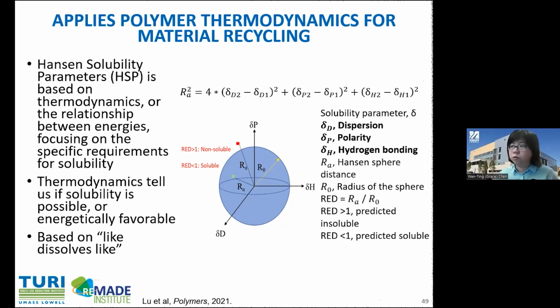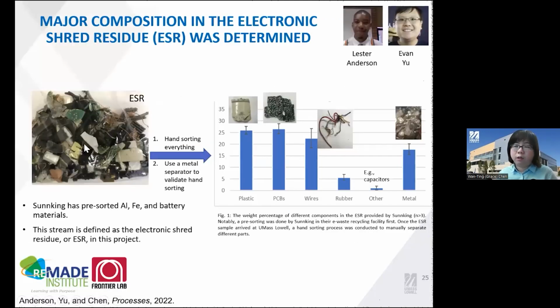So with that in mind, I would like to explain why we need to learn this polymer mixing thermodynamics. With this, for example, if the waste we would like to recover, we know its solubility. Okay, we'll be able to formulate and identify a solvent that could help us extract this specific polymer. And this is especially important for relatively mixed plastic waste, such as the electronic waste that I show here. So this is an electronic waste residue where an e-waste recycling company has already taken those valuable parts. So first we study what's inside of these electronics, and then we found plastic accounts for about a quarter, like 25%. And among these plastics, the majority of them is actually made of polystyrene.